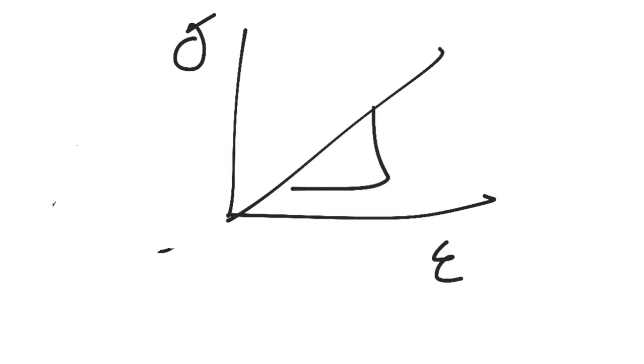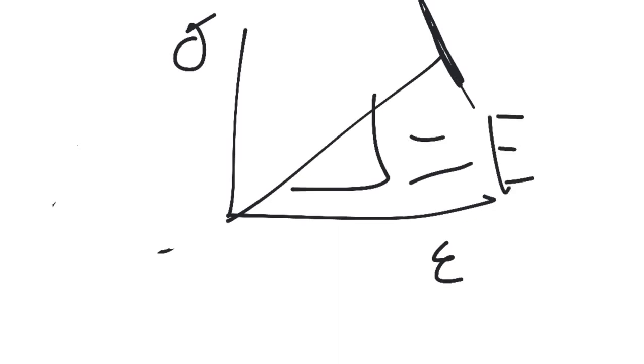Make sure that you take your gradient as far away as possible from that limit of proportionality, because if you even go slightly beyond it, then your gradient starts to include something that's a curve. It's going to really skew your Young's modulus, which should be constant for that material when it's obeying Hooke's law. So very important that you take that into account.